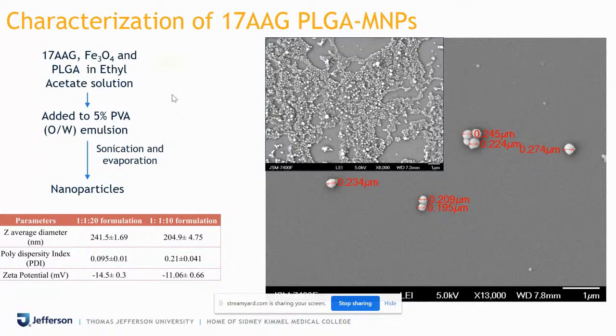I created two different types of formulation, one is 1:20 and one is 1:10. The Z average particle size is shown on the screen, it is 241 and 204. Now the table which I've shown, these were the experiments from dynamic light scattering. These dynamic light scattering experiments can sometimes be difficult for reviewers to understand, so we confirmed these experiments using SEM, that is scanning electron microscopy. The images are shown just next to it.